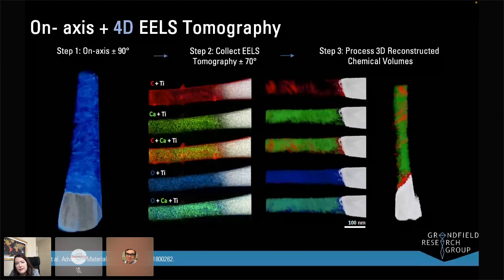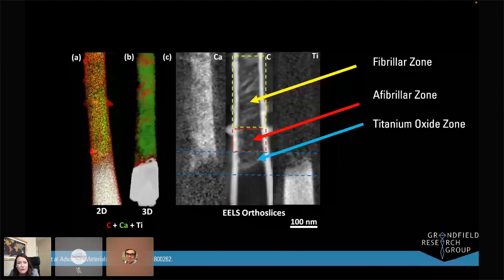With a four-dimensional data set, we can explore it. For example, we can take this volume and take a slice anywhere within the center of it, and look at the chemical signals. We can see our calcium containing zone, a fibrillar zone where our carbon is representing our collagen fibrils, and we can look at where our titanium dioxide is located.